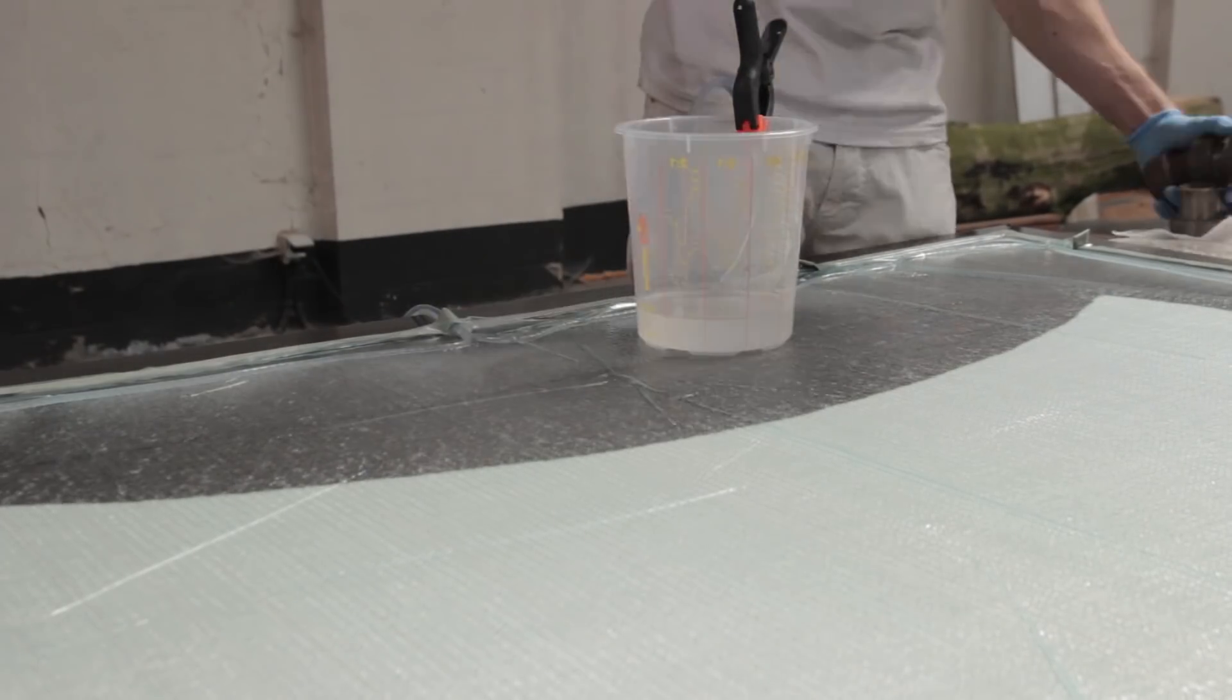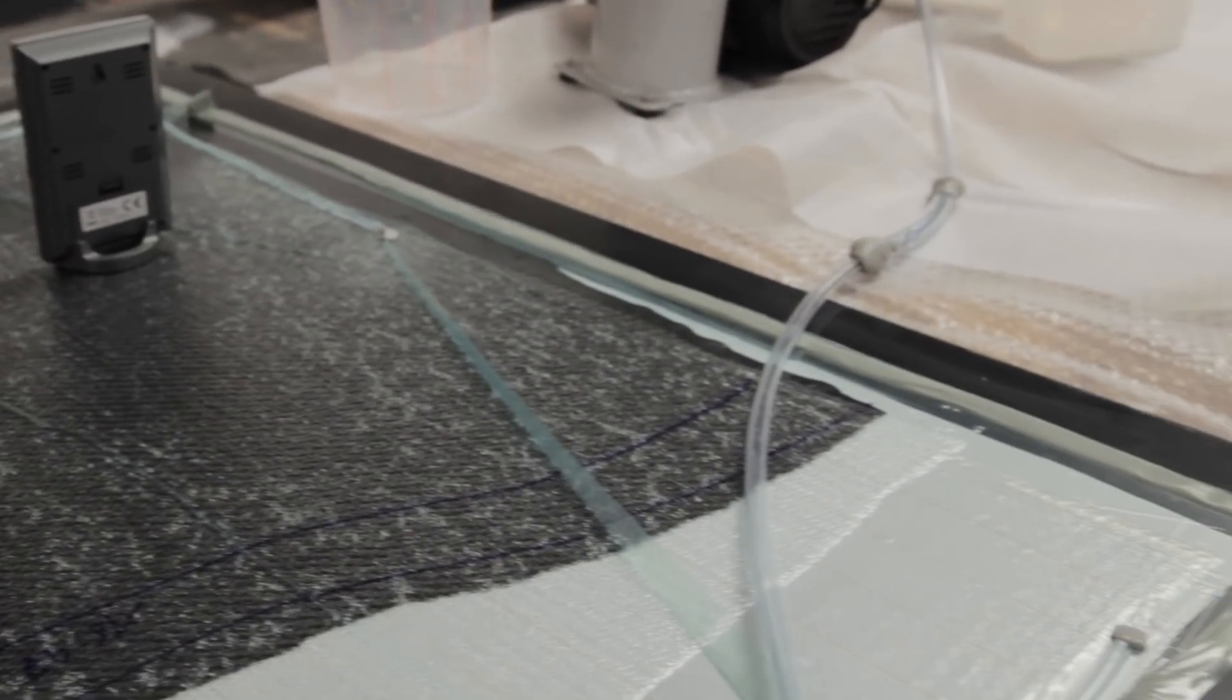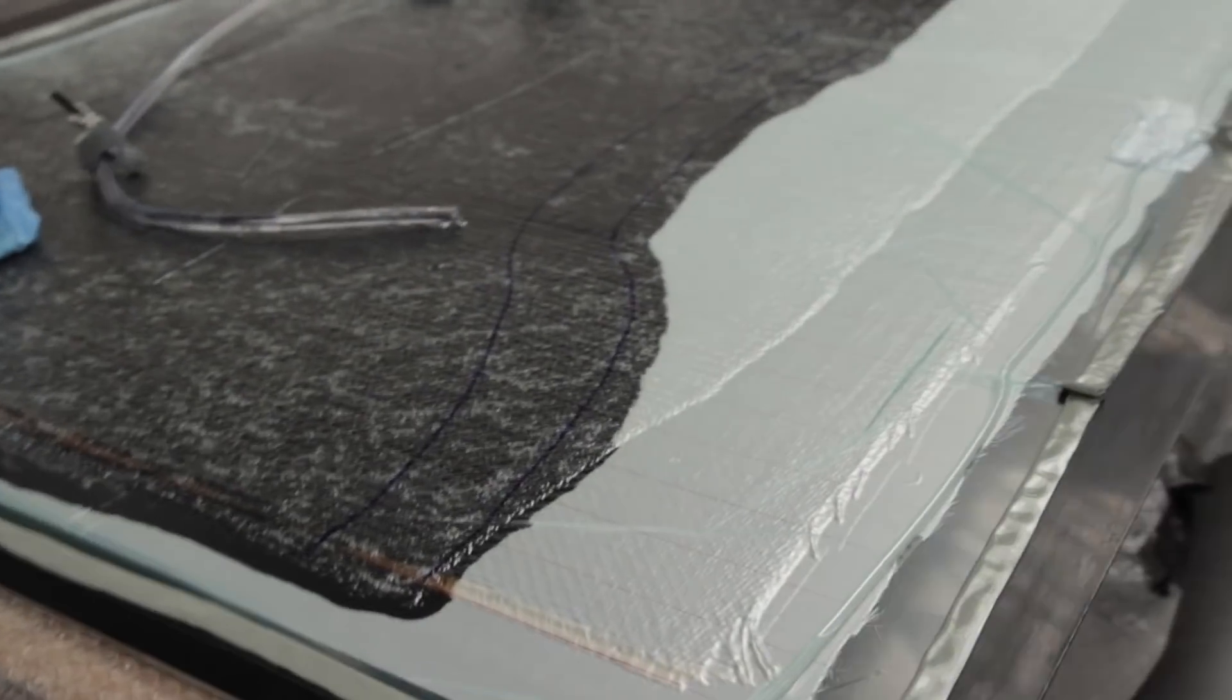Mostly you can get away with it if you go till the ends of the infusion. You close all the clamps and then just by pressure the bubbles will get smaller because there is less vacuum and there is a good amount of resin, it will make the bubbles go smaller. This is exactly the same with infusion resin, but I mostly degassed it just to avoid already having those bubbles going into it.